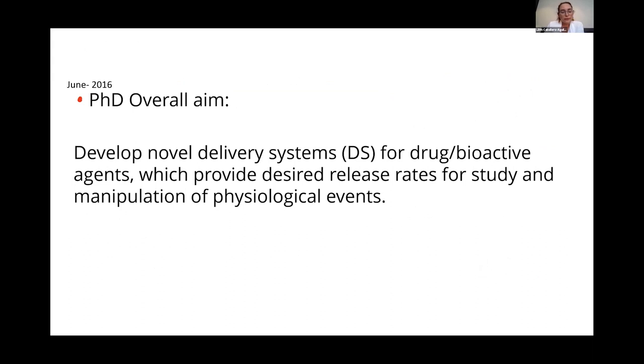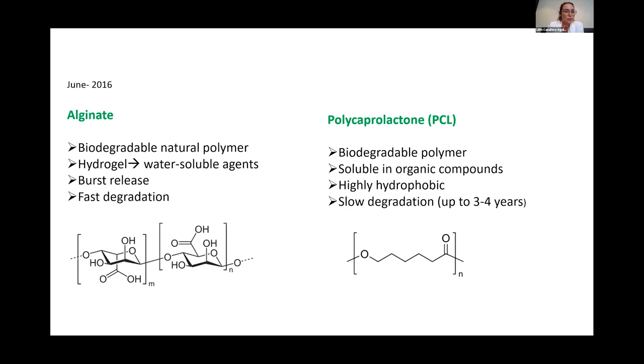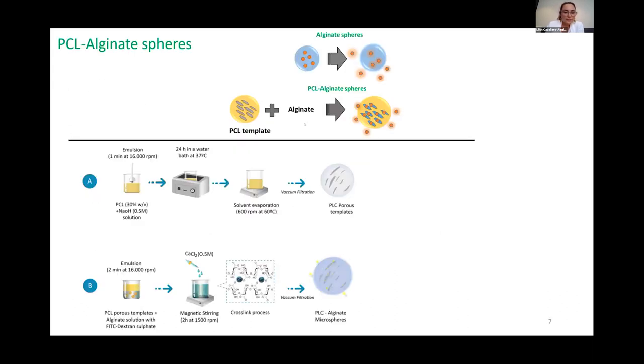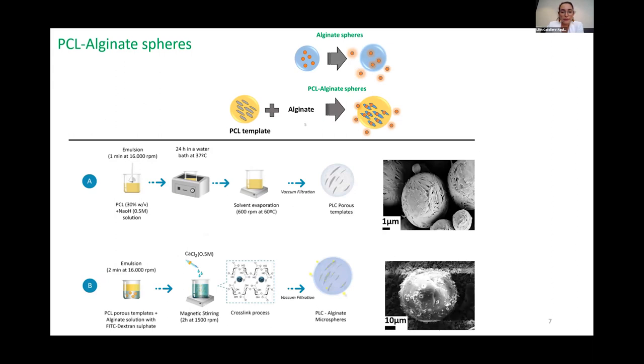So the overall aim of the PhD back in June 2016 was to develop novel delivery systems for drug or bioactive agents to provide desired release rates and basically to study or manipulate some physiological events. So it was very general. So I decided to work with two different polymers. One, alginate, you know pretty well, is a hydrophilic polymer, and combining that with a hydrophobic polymer, which is polycaprolactone, and by creating these PCL templates that we then fill with alginate, we aimed to control the release profile of certain molecules, and it happened that way.